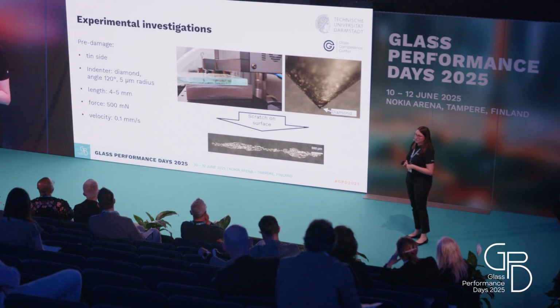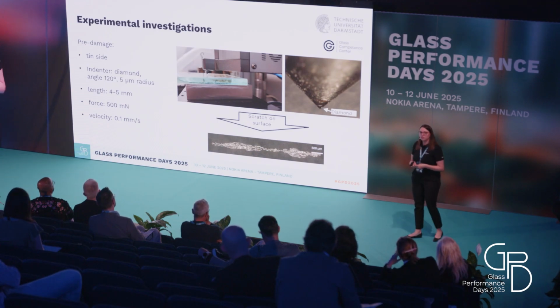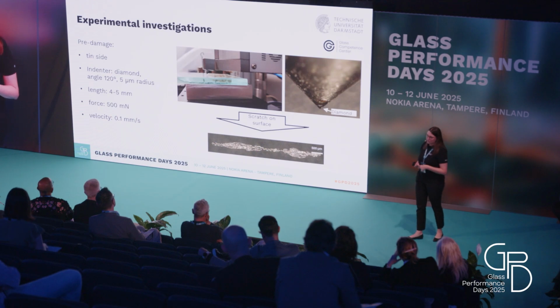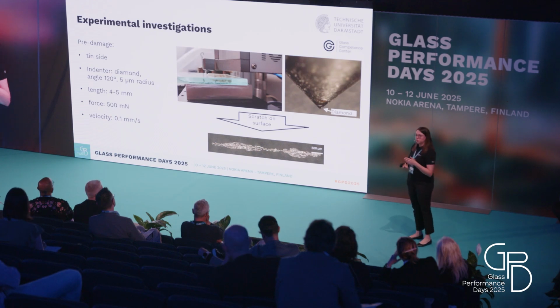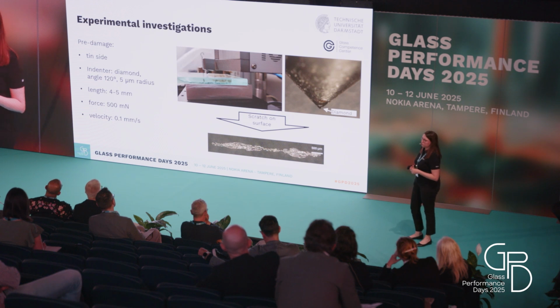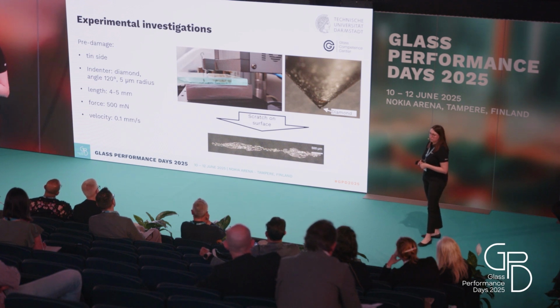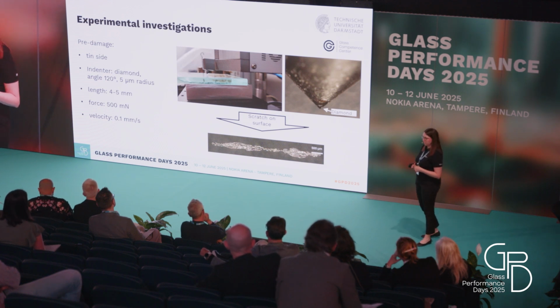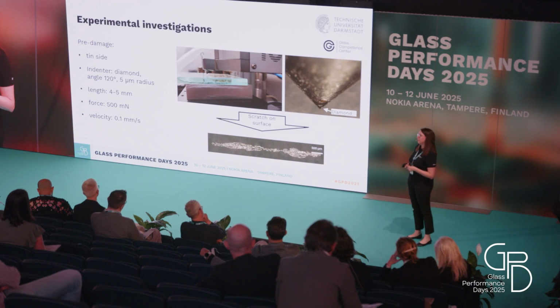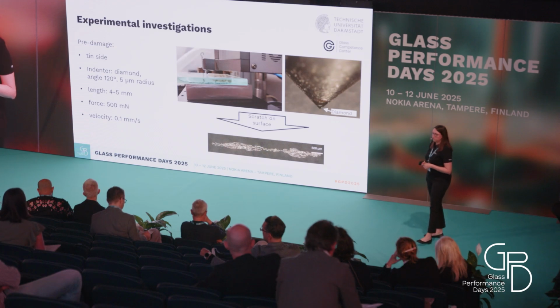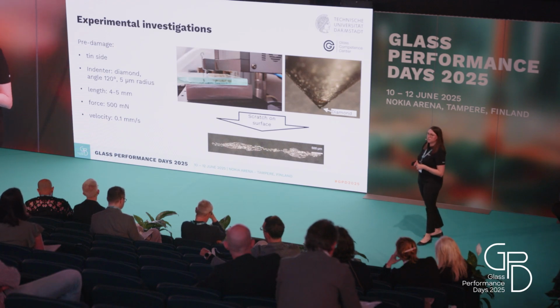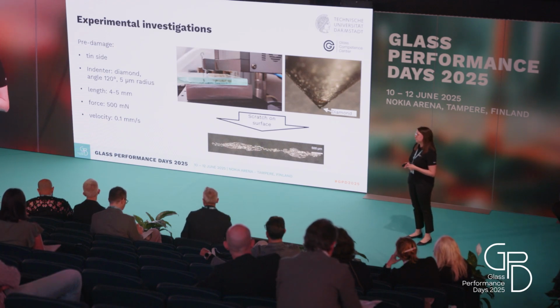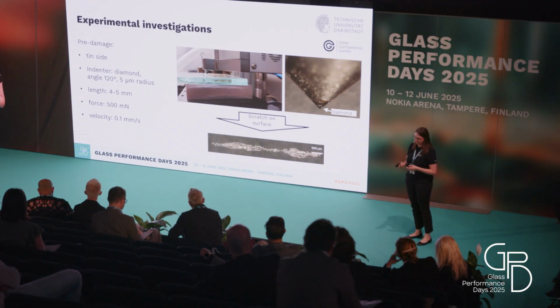So for the pre-damage, we used the universal surface tester, and the pre-damage was always introduced on the tin side. The indenter we used was made of diamond, with an angle of 120 degrees and a 5 micrometer radius. The length of the introduced scratch was approximately 4 millimeters. The force that we applied was 500 millinewton, and the velocity was 0.1 millimeters per second.